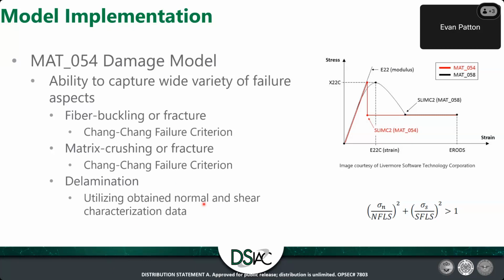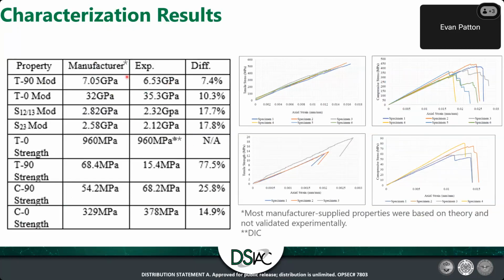So that was one of the tricky things with this material, and that's partially due to the unidirectional nature of it. You know, there's such a high difference in the anisotropy within the material. Your x-axis is much stronger than your y-axis, and you can pretty much see that in these properties here, the moduluses and the failure strengths. So that made it pretty tough to deal with. Gotcha. Okay.